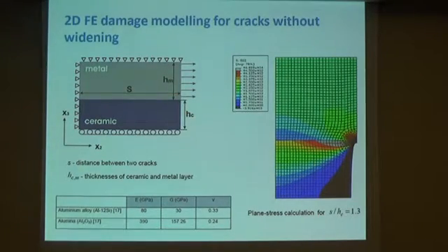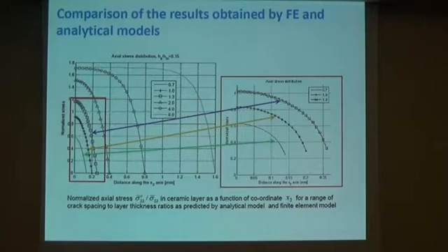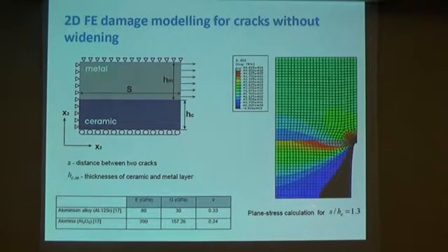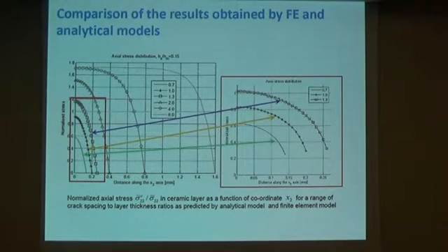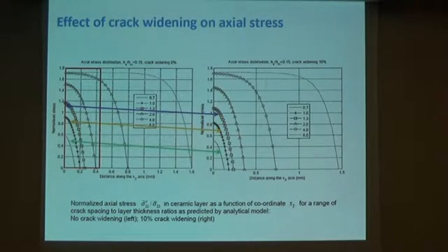But to know more, we need to perform a finite element analysis, and in that we uncover some interesting details. For example, this black region near the crack surface, which I will talk about in a minute. This is a comparison of analytical predictions and finite element results. We found that they are in good agreement with each other, so our analytical model is okay. And this is when we take into account crack widening, and we see that when crack widening is taken into account, the maximum stress value is reduced.